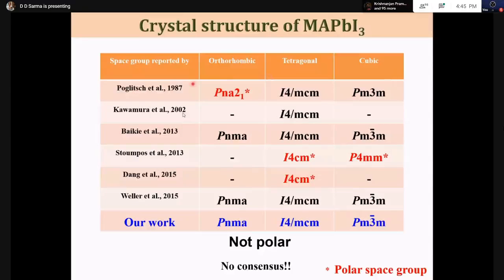Now, the reason this confusion exists in X-ray diffraction, which is also actually a limitation of our work, is that this polar and non-polar question is connected to MA. PbI3 is essentially non-polar, the cube that I showed you. It is the MA that is a non-symmetric, asymmetric molecule, and if it arranges itself, it can arrange in a non-centrosymmetric way and can influence also this structure. So it is essentially related to this. But this has only carbon, hydrogen, and nitrogen, and they don't scatter X-ray very strongly, and therefore X-ray structure determination is not a very good sensitive way of trying to figure out what MA is doing. So one needs to do other things.